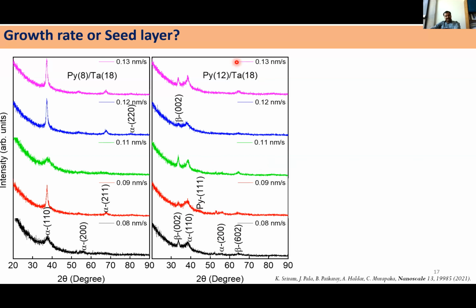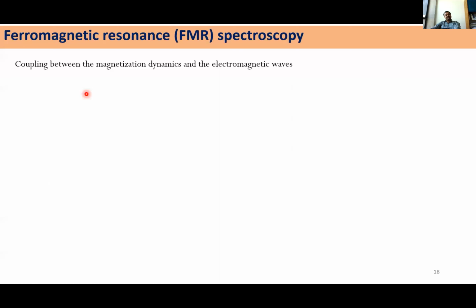So we could conclude that it is not only the growth rate that affects the crystalline phase of tantalum. However, the seed layer can also affect the crystalline phase, as you can clearly see here. If you deposit on 12 nanometer, irrespective of the growth rate, it is mixed phase. If it is 8 nanometer, irrespective of the growth rate, it is alpha phase. Okay. And now we have chosen the spin pumping technique.